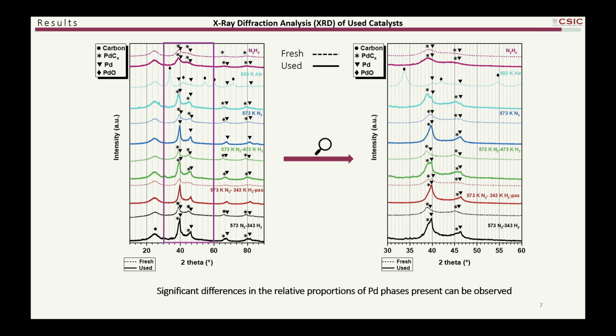And the most significant change is observed in the catalyst calcined in air, because we can observe that the metallic palladium and palladium carbide phases rise at the expense of palladium oxide. So with this characterization, we can conclude that the reaction medium modifies our catalyst.